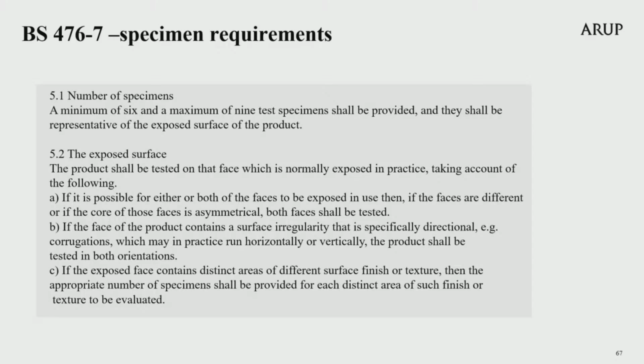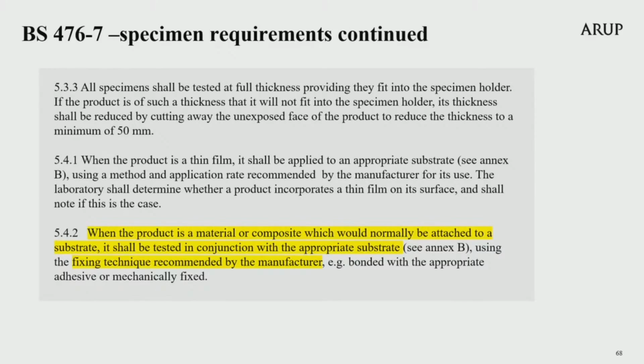If the face of the product contains a surface irregularity that is specifically directional, for example corrugations, the product shall be tested in both orientations. If the exposed face contains distinct areas of different surface finish or texture, then the appropriate number of specimens shall be provided for each distinct area of such finish or texture. All specimens shall be tested at full thickness or cut away, as I explained earlier.